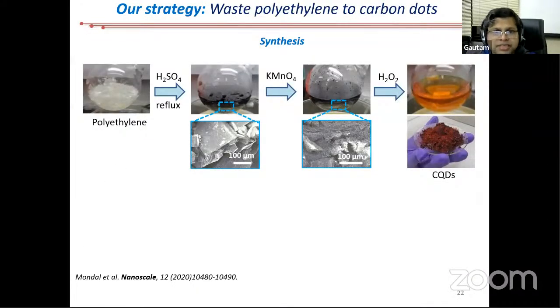So I can see the different stages. This is actually a plastic bag which we picked up from a dustbin, and then you can see when you put H2SO4, it becomes carbon, it becomes graphene. Okay, and then when you put H2O2, it forms these dots, and these dots are soluble in water. So you can see this beautiful color. This solution is stable for several years.